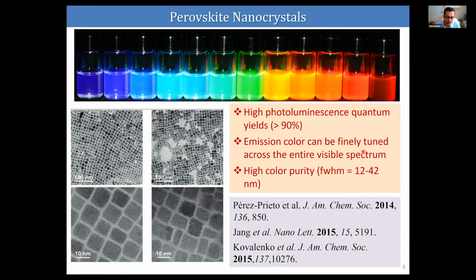Before going to the main topic of today's lecture, I just want to show what is happening in our laboratory on perovskite nanocrystals. Why are these materials important? Because of the three reasons summarized here. They show very high photoluminescence quantum yield, typically about 90%, and you can get nearly 100% in many cases. The emission colors can be easily tuned across the visible region by simply changing the halide anion, which is chemically very easy. And you can get very high color purity, with a full width at half maximum as low as 12 nanometers.